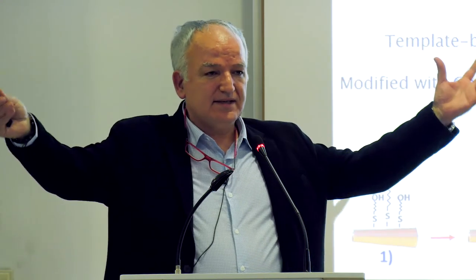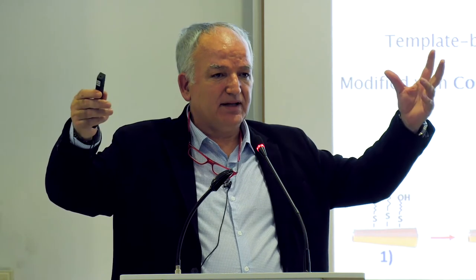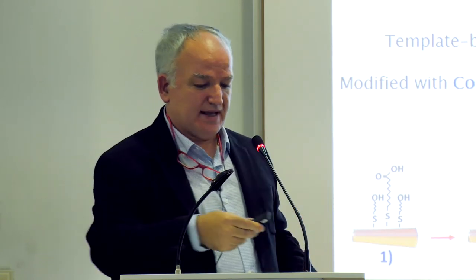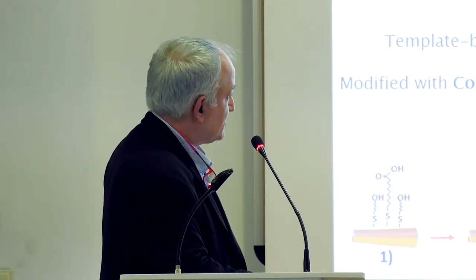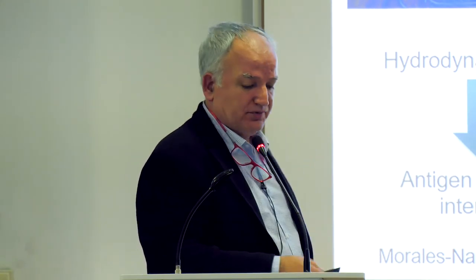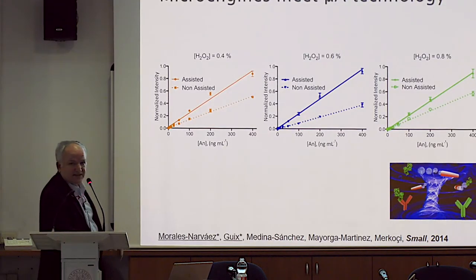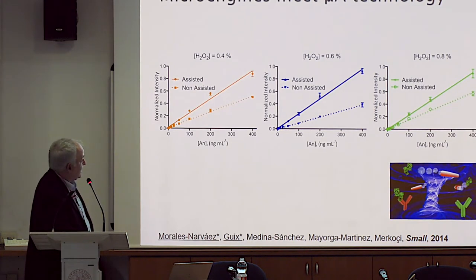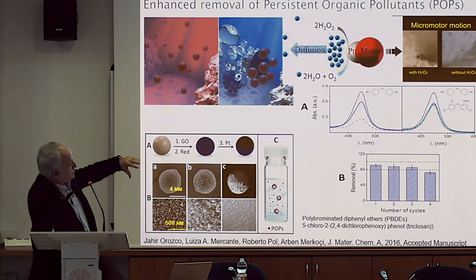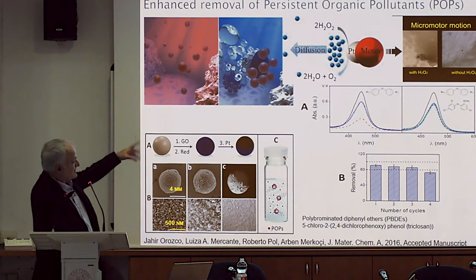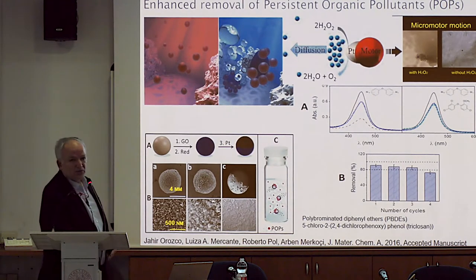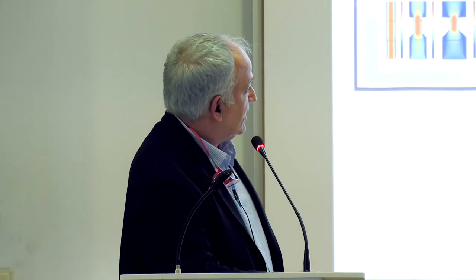The idea is to use these devices, as I said before, we release these in the matrix, in the sample, and then applying this magnetic field, we bring this to the surface of the sensor, and we are able to detect even single compounds. We use this, for example, to accelerate the diffusion, which is very important for microfluidics, and you can see here the increase of the sensitivity when these devices are used, or even to remove some contaminants. These are still some motors we used to remove some contaminants in water, and so on.